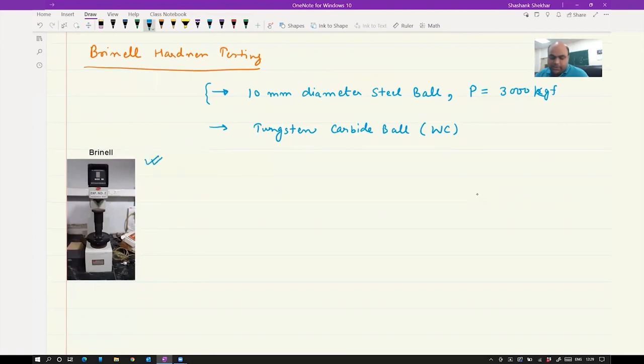And this is the setup. So this is the Brinell hardness tester we have in our lab here at IIT Kanpur. Okay, so we show this test to all UG students in our department. So you place your sample here. Okay, so you have anvil. Okay, and then indenter is here on the top. Here, okay, so you can see this is your indenter. So you place your sample, okay, and then you make an indentation, then take out the sample, go to microscope and see the indent impression as I discussed just before.